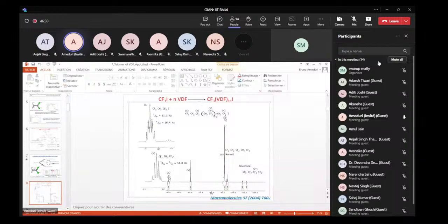So at minus 40 ppm, you can see this end group. And again, you have this match with a value of 2 and a value of 3 compared to that. So by calculating this from NMR, it's possible to have 11 units.